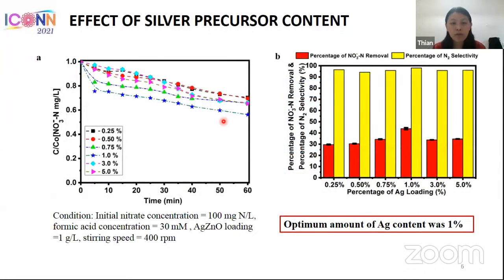Then we go a little deeper. We study the effect of the silver content in the photocatalyst. So what we can see here is, let's look at figure B. It is more clear, I guess. As we increase the silver content in the photocatalyst, there is a gradual increase, the red bar here, in the percentage of nitrate removal, but beyond 1%, which is 3% to 5%, the percentage of removal actually decreased.